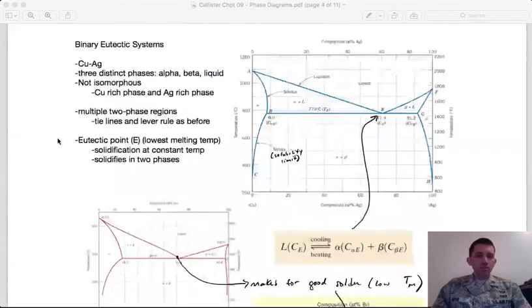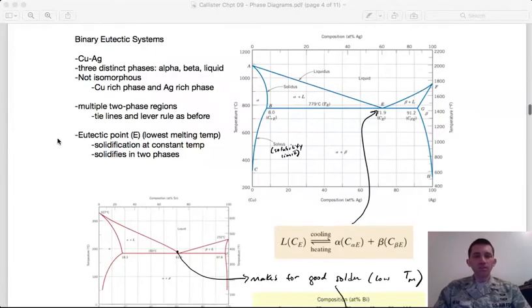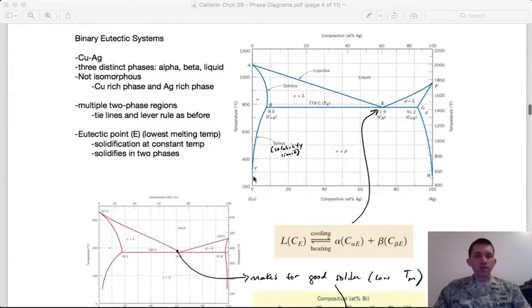Okay, so what happens if we have a binary system but it's not isomorphous, meaning that I don't have 100% solubility of my components? That would be the case of copper and silver, and this forms what we call a binary eutectic system. And in this case, we actually have three phases: alpha and beta, which are both solid phases, and then the liquid phase.